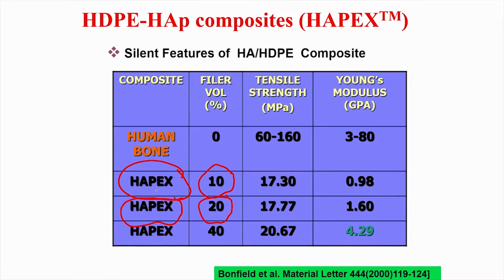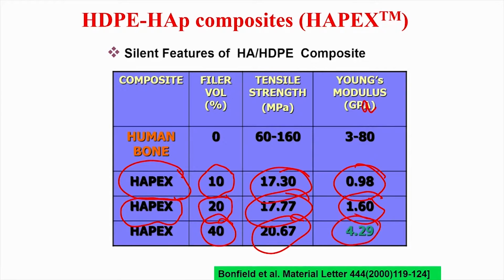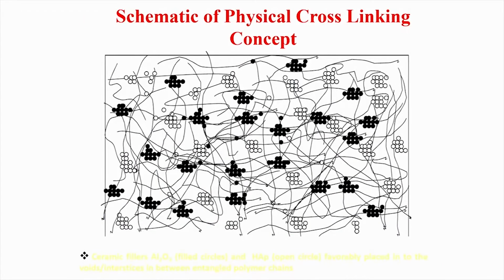High density polyethylene and hydroxyapatite were developed for middle ear orbital implants, and their strength was around 17 megapascal and elastic modulus 0.98, close to 1, or 1.6 gigapascal. We have developed with significant alumina and hydroxyapatite a material with much higher modulus and strength properties. So what is the rationale, or the physical principle, which can be used to explain the enhancement in the physical properties? You have the alumina particles and the hydroxyapatite particles, shown here by filled or open circles, and you have the high density polyethylene chains running around these particles.